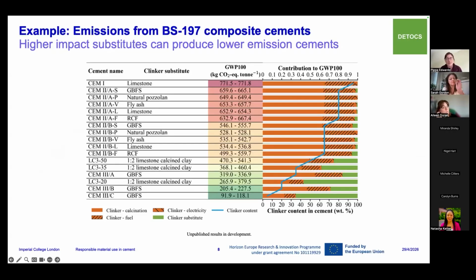And calcined clay is particularly promising because it's produced from widely abundant common clay deposits and at a comparable cost with conventional cement. And the performance is there as well. Limestone calcined clay with 50% clinker has been experimentally validated to have comparable mechanical performance to conventional cements. So we can meet our 50% clinker factor target with calcined clays, but what can we do to go further?